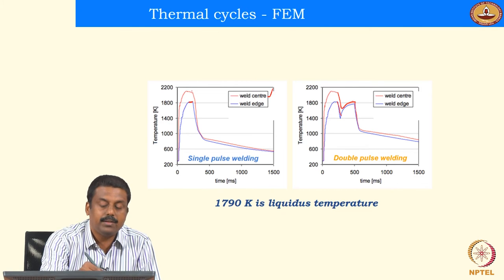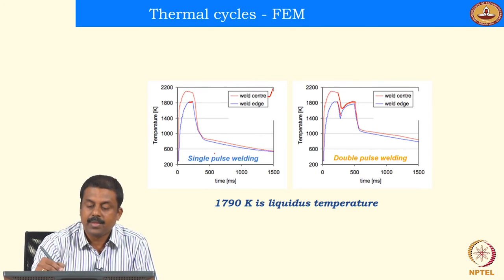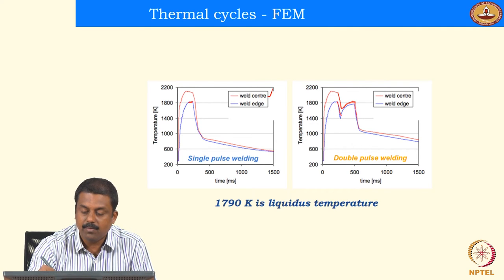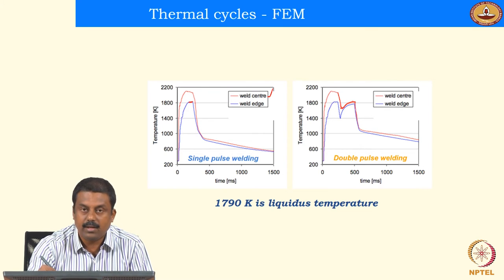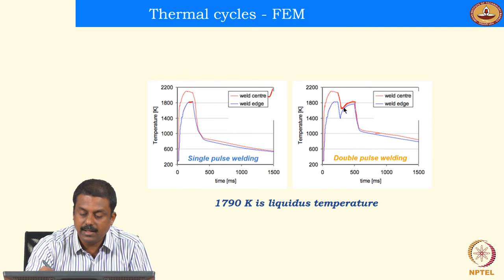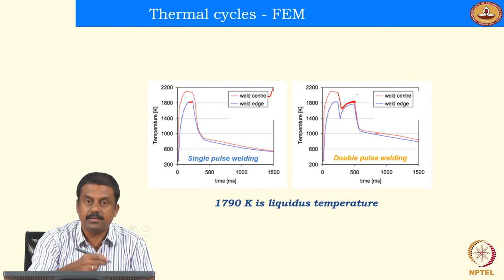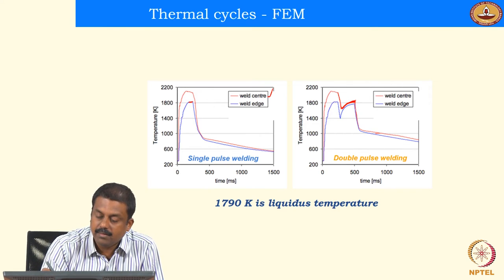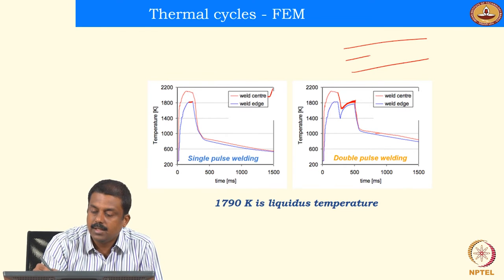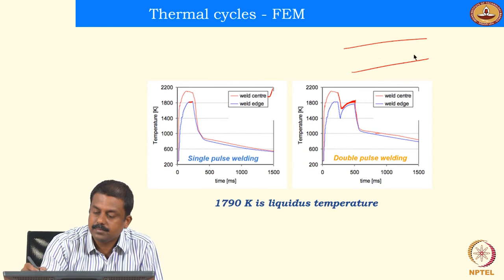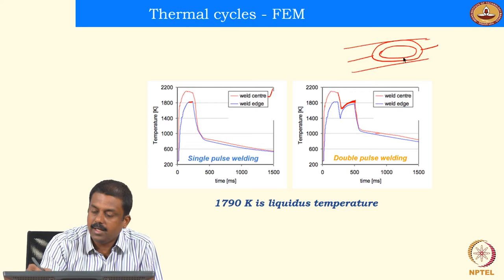So in a single pulsing, we are cooling continuously from solidification temperature to room temperature, whereas in double pulsing, instead of cooling to room temperature, upon cooling to some temperature where we have a complete solidification, we increase the temperature slightly higher, and then subsequently we cool to room temperature. And this increase in temperature can have a very positive effect by homogenizing the microstructure and the composition. Which we already saw in the optical microscopy, because of this reheating, we form a secondary weld nugget. So this is the first weld nugget. And because of the reheating, we have melting in the regions, and we form the secondary weld nugget, because of this heating.